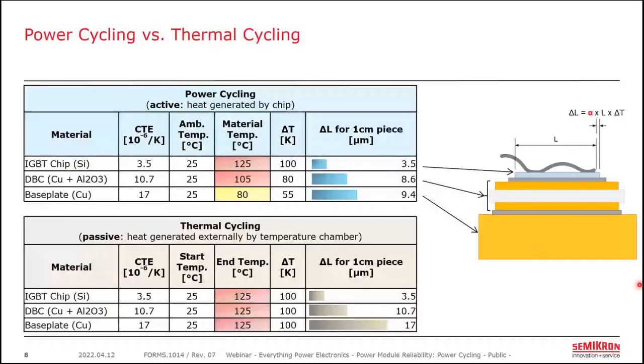So at this point, I want to distinguish between what we call power cycling and thermal cycling. If we consider a power module mounted to a heatsink, we define power cycling as the process wherein the semiconductor chip is the source of the heat, as would be in a real-world application. And this heat causes a temperature gradient across the module as heat flows from the chip down through the base plate and out through the heatsink. That is to say, different parts of the module are different temperatures.